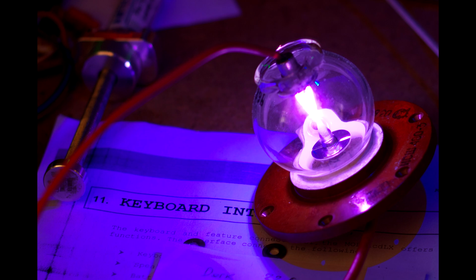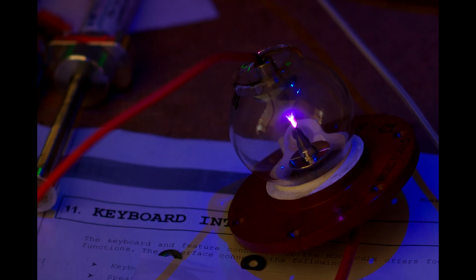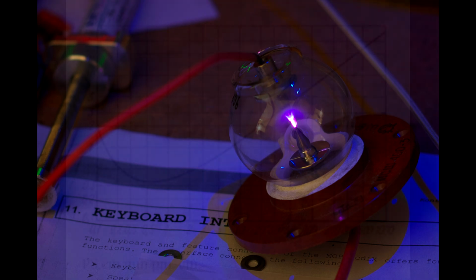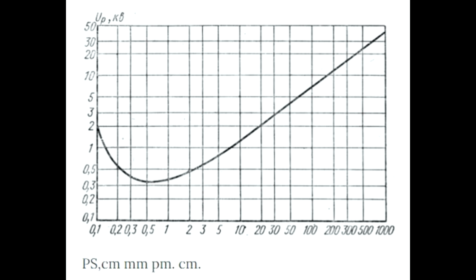While I was playing like a kid with my new low pressure lamp, low pressure toy, a very big surprise was waiting for me. Actually, I concluded wrong that the lower the pressure, up to 1 millimeter of mercury or 100 Pascal, the lower the voltage I need to break down the distance between electrodes, and the lower the interference. I wasn't right. When I connected this lamp to my clock and started it, it started to give even much more interference compared to xenon under high pressure.